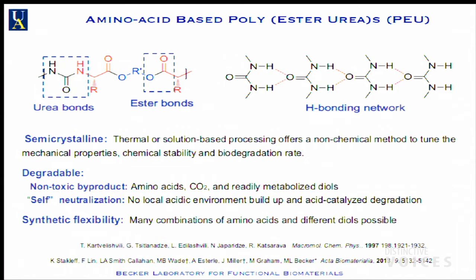These materials are strong because they have a very strong hydrogen bonding network that's enabled by the urea. The thermal and solution processing can be controlled by what type of amino acid it is, what the molecular weight is, and what type of diol you have. So the library space is enormous, and we've literally made hundreds of these materials. When they degrade, you get amino acids, carbon dioxide, and readily metabolized diols, all of which are excreted quite readily, and it's easy to prove.